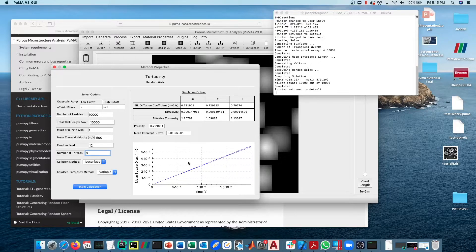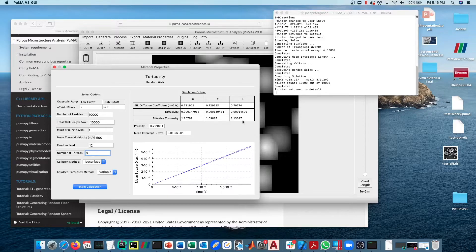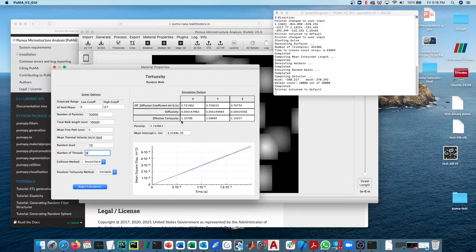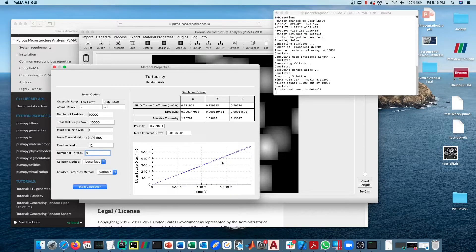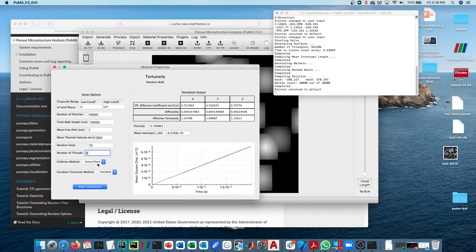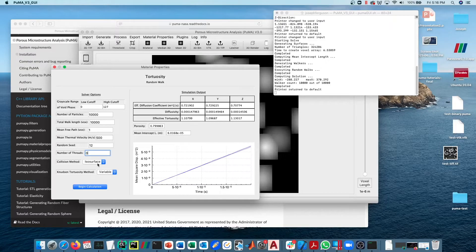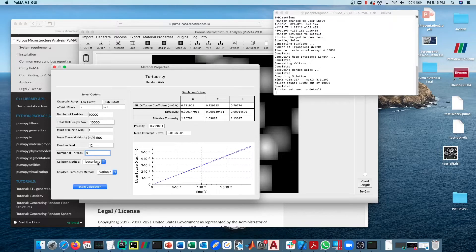Here we go, we can see that now we have an effective tortuosity value of 1.107, 1.09, 1.13. If you notice, these are slightly different, although still fairly close to the tortuosity values that we had in the other solvers. There are two reasons for that. The first is going to be the surface representation—using an isosurface is actually a more accurate representation of the surface, so if it's between the two, I would trust this random walk method more than the continuum solver.